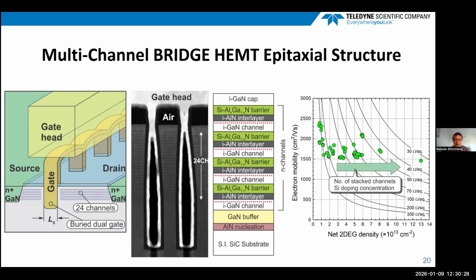So on the right, I plotted the electron mobility as a function of net 2DEG density. Like I said, the net 2DEG density can be controlled by the number of channels and the doping concentration. And we could obtain a very high charge density of up to 1.3 times 10 to the 14th, which is more than 10 times as large as the single channel gallium nitride HEMT, while maintaining a reasonably high electron mobility of 1500.